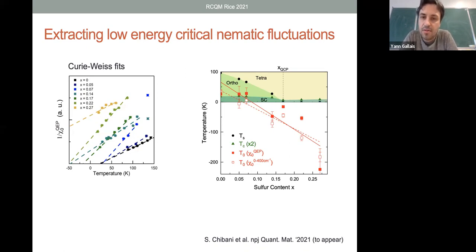And this is the result on the phase diagram on the right, where the open and filled symbols represent different determinations of this T-nematic. What is relatively striking is that even though there is some scatter in the points, it's pretty clear that there is a shift between the doping where T-nematic extrapolates to 0 and the doping where T_S extrapolates to 0. So there is a significant shift in terms of sulfur composition between the thermodynamic QCP and the bare QCP that would happen where there was no coupling to the lattice.